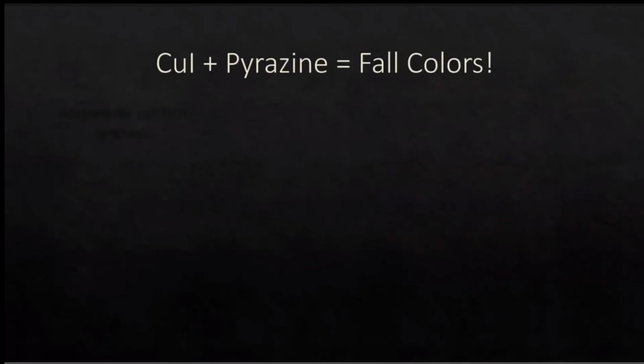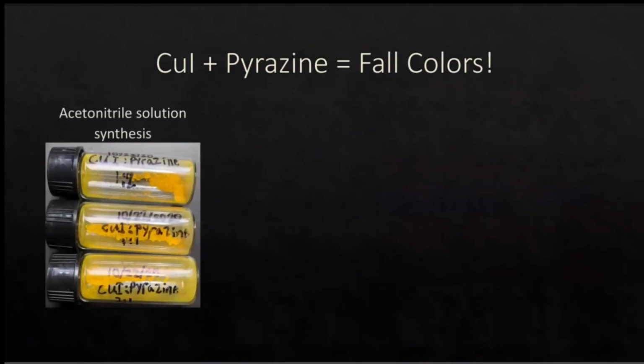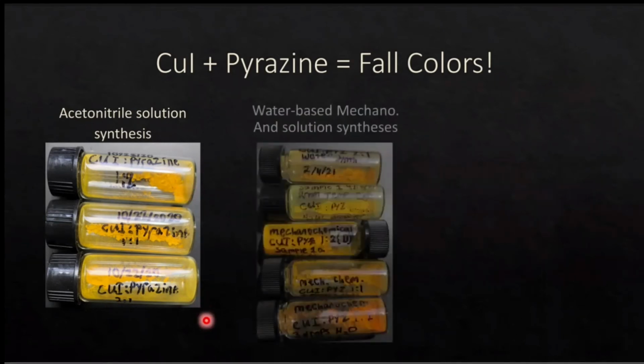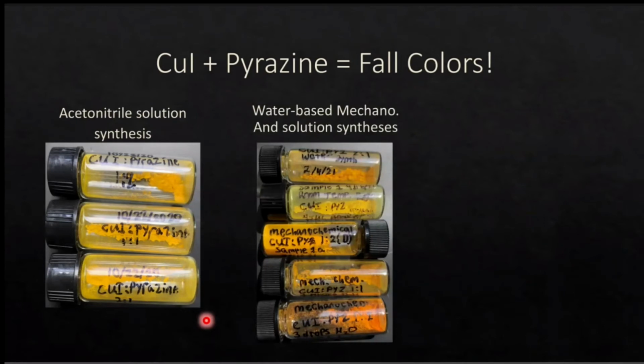So the system which we focus the most on is copper iodide and pyrazine, which just so happens to make a lot of pretty oranges, yellows, and reds. In acetonitrile solution synthesis, we found that no matter what our metal to ligand ratio, we always seem to produce this yellow polymorph that has also been reported very commonly in the literature. So we wanted to see if this would change if we went through a mechanochemical pathway. And so first we tried a water-based mechanochemical